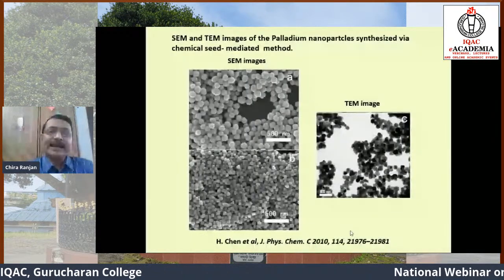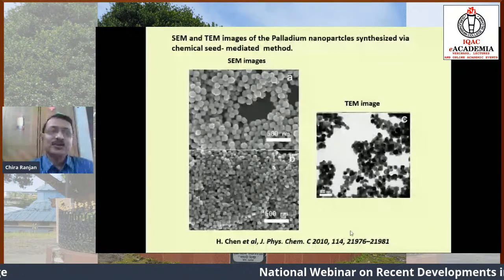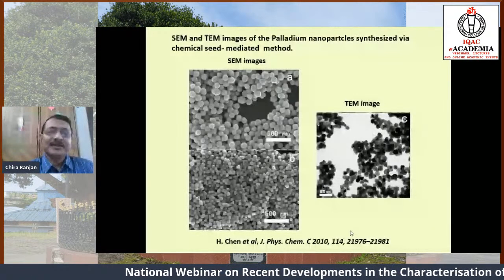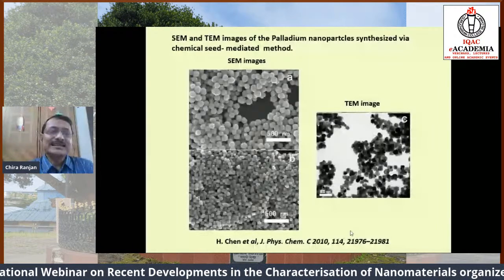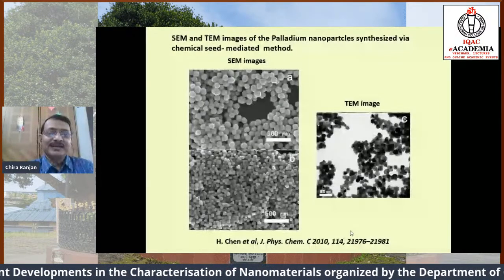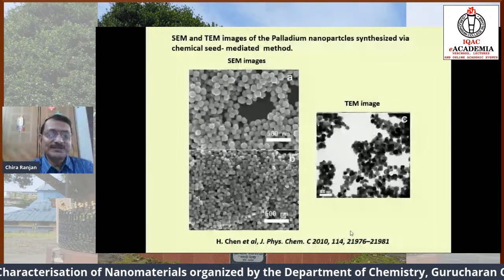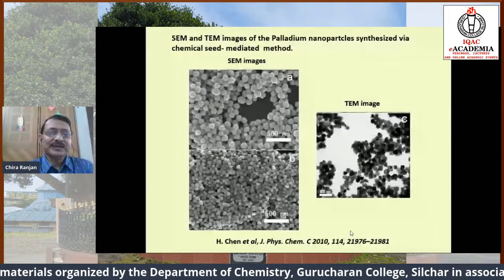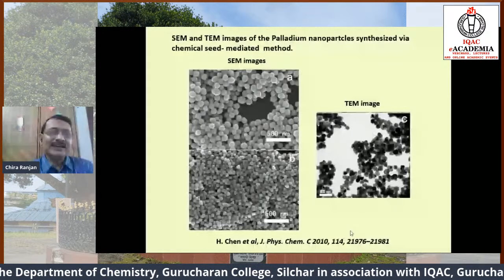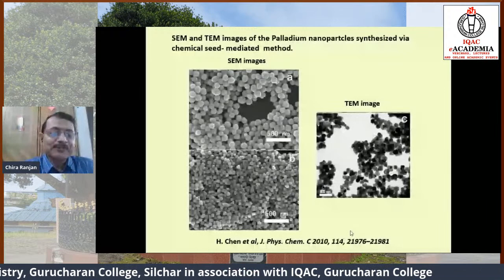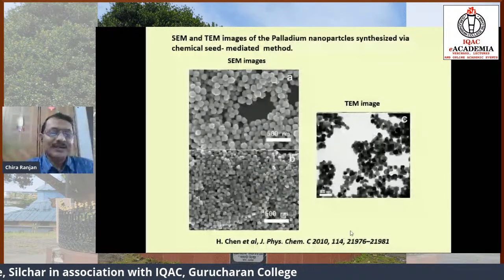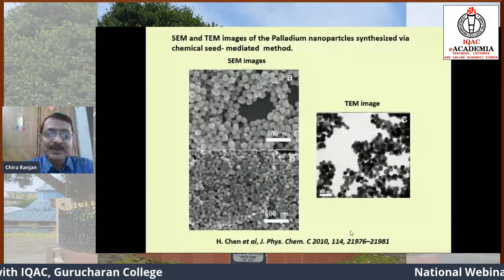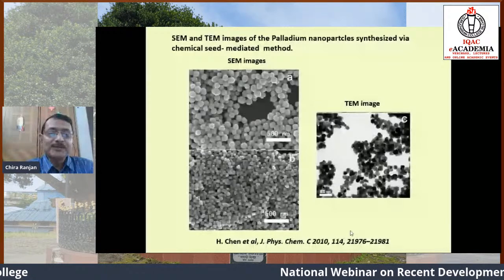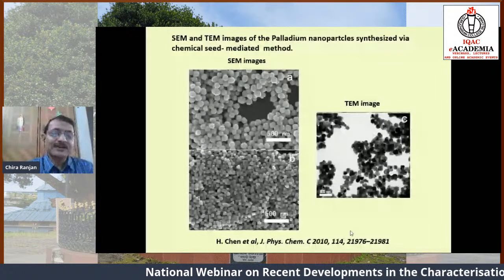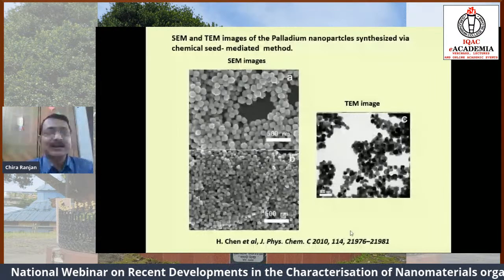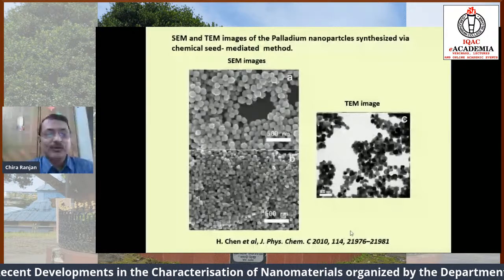Here are some palladium nanoparticles, which were synthesized using a chemical seed-mediated method. You can see the SEM images are very clear. The roughly polygonal shapes are visible from the SEM images, though the TEM image is not very clear. So sometimes for certain types of particles, SEM images could be better, and on some occasions, TEM images